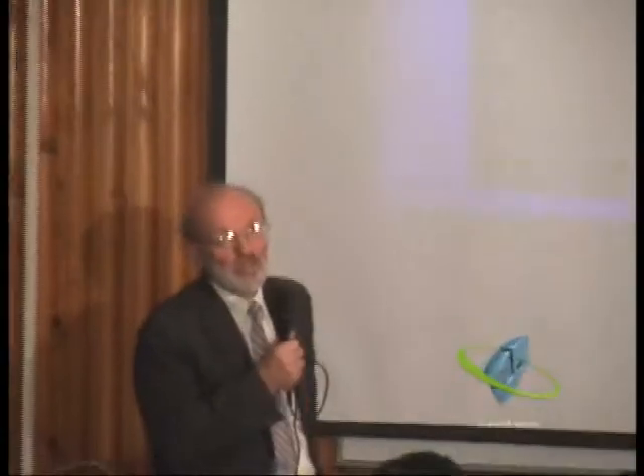So, how can we solve the chipping problem? Basically we have to cool this material such that between the softening temperature and the glass transition temperature, we slow down the cooling rate. Because if we slow down the cooling rate, there will be limited difference in temperature between the inside and the outside of the porcelain. Once we're below the glass transition temperature, then we can increase the cooling rate again. But the critical region is between the glass transition temperature and the softening temperature.